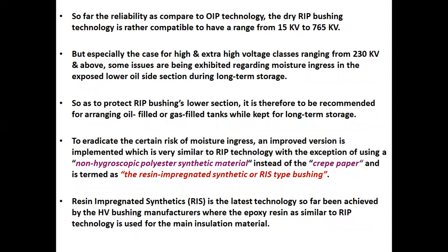So, for reliability as compared to OIP technology, the dry RIP bushing technology is rather compatible, with a range from 15 kV to 765 kV, but especially the case for high and extra high voltage classes ranging from 230 kV and above. Some issues are exhibited regarding moisture ingress in the exposed lower oil side section during long-term storage.